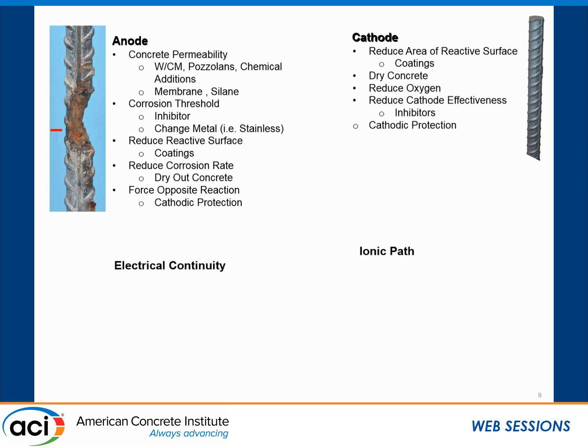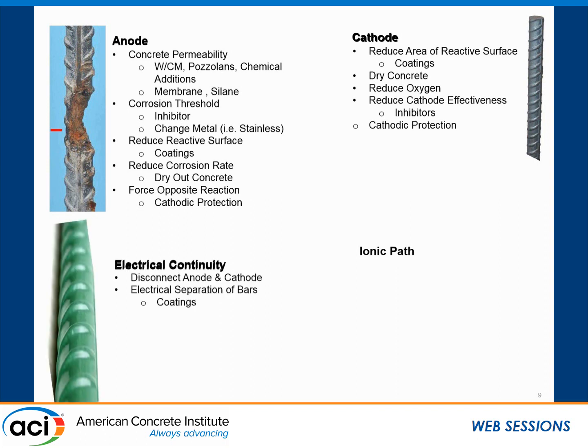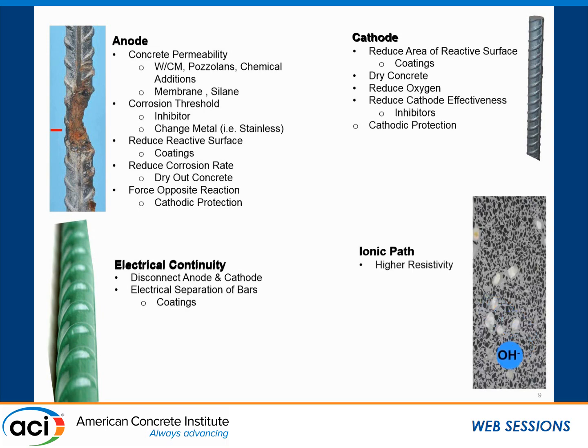Again, we can reduce the active area of the corrosion surface. We can dry out the concrete. We can use inhibitors that are effective at the cathode. And again, cathodic protection. For electrical continuity, we have to disconnect the anode and the cathode. Best example of that is like a coating on the reinforcing steel. There's no place for the anode and cathode to form unless that coating gets damaged.